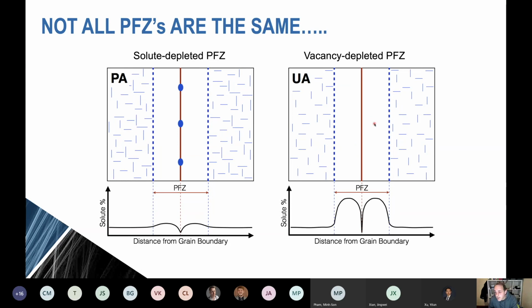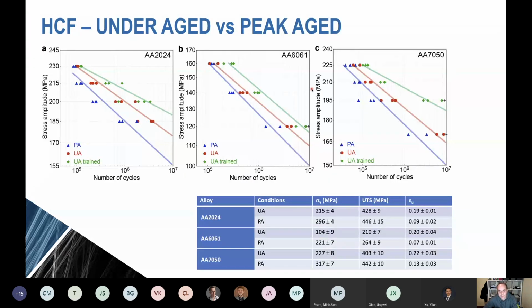Now, if this is correct, you would expect that you probably can have better high cycle fatigue performance in the underage materials compared to the peak age materials, even though this material would be macroscopically weaker. And so indeed, we've done exactly those sorts of tests on all sorts of materials. I show you here, these are classic SN curves. They're generated fully reversed axial loading on smooth samples.